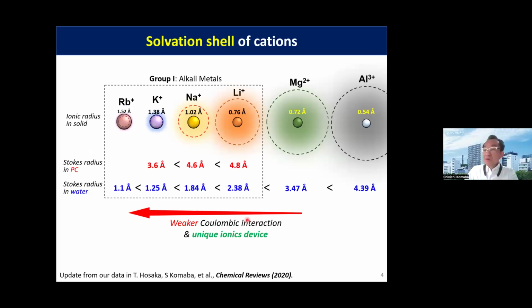So when we compare the ionic size, of course, lithium is the smallest among the alkali metal ions. However, when lithium, sodium, potassium, and rubidium ions are dissolved in a liquid electrolyte, the cations have Coulombic interaction with polar organic solvent or water molecules. In the case of propylene carbonate, we see some Stokes radius. This is the size of the solvation shell.